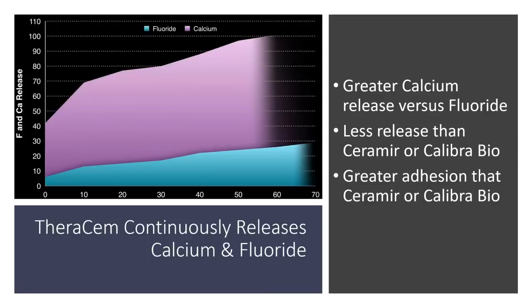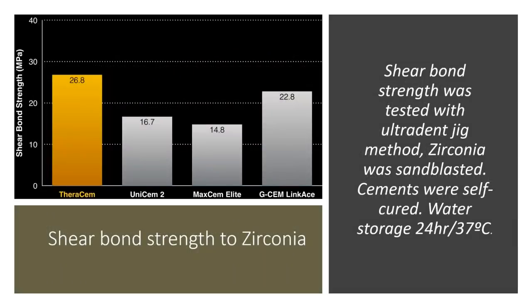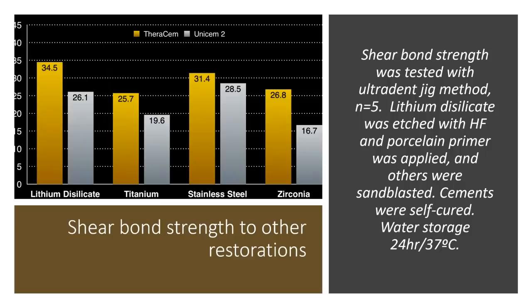So where do all these numbers fit in? It does have greater calcium release than fluoride release, but understand Ceramir and Calibra Bio, which are not resin cements, have far greater calcium release. But again, Theracem will have greater adhesion. So you have to know what to pick based on retention, isolation, and where your margins are. It's got great bond strength to zirconia. In comparison to the others, you can see it's right there. And to other restorations, whether it's lithium disilicate, metal, or zirconia. So I'm going to show you cases of all.